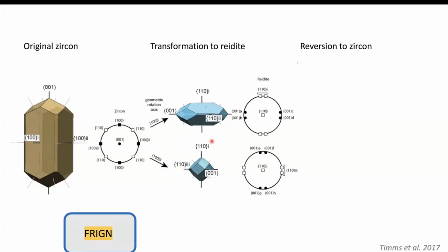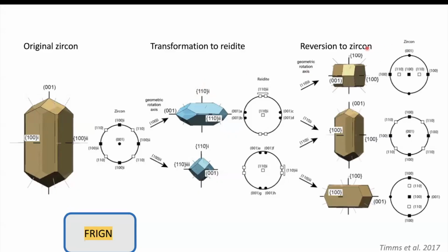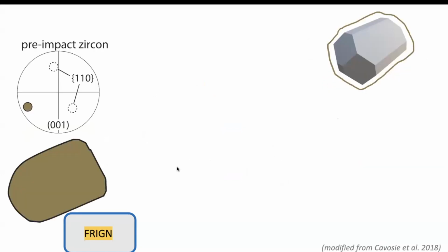So I haven't seen experimental evidence for this, but it has been theorized that the back transformation follows the same rules as the forward transformation. The idea is that the 110s of Reidite transform into the 001s of the zircon, just like what we had before, but this time in 3 variations, which are all mutually orthogonal. There is about a 5-degree spread in this relationship between natural zircon and natural Reidite, and the back transformation is expected to introduce about another 5 degrees of spread.